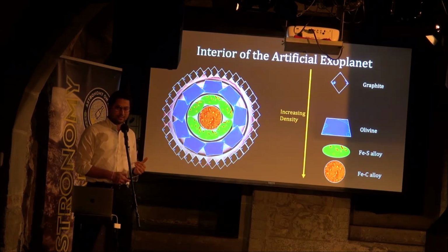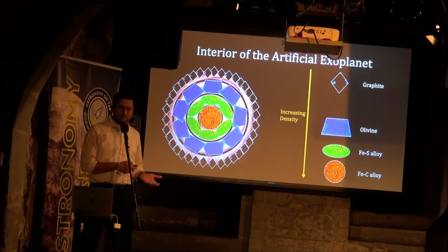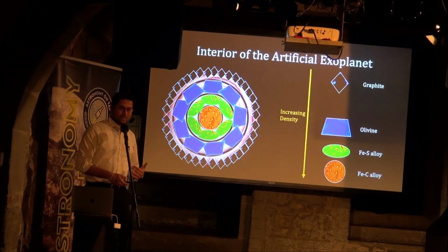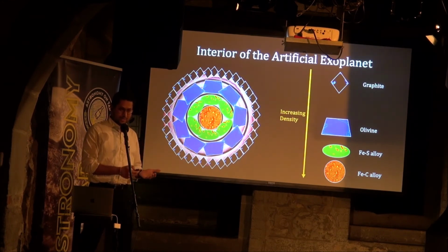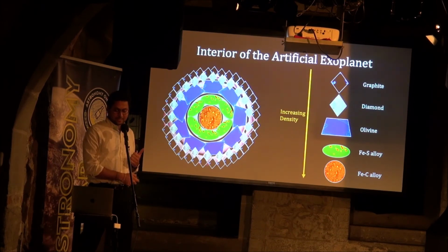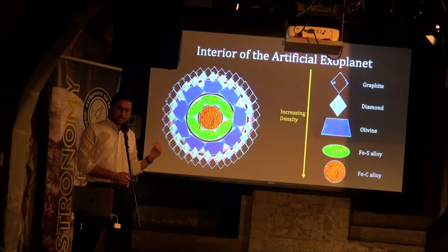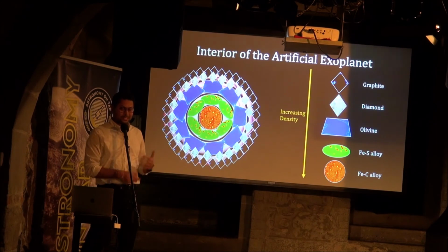There are different layers in the planet. But there is one interesting thing. These experiments I ran to pressures of 40,000 atmospheric pressure. But if you go between 50 to 80,000 atmospheric pressure, then you actually turn graphite into diamond. So if the pressures are slightly higher, the bottom layers of the graphite, which are at higher pressure than the top layers, would turn into diamond. So essentially, this kind of structure would be there in that planet.